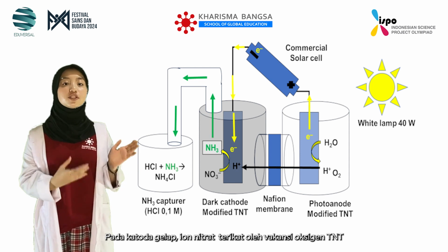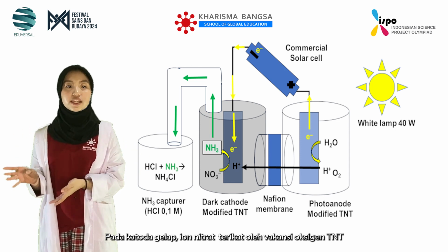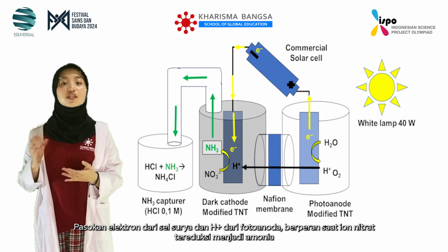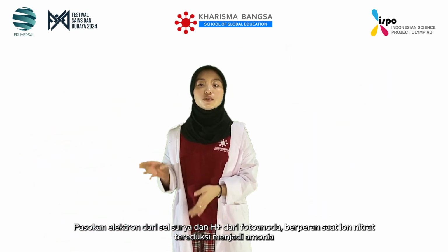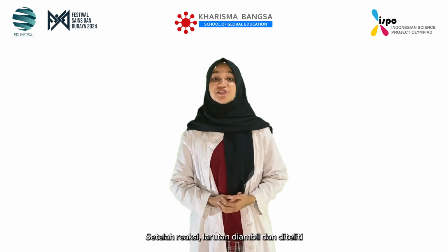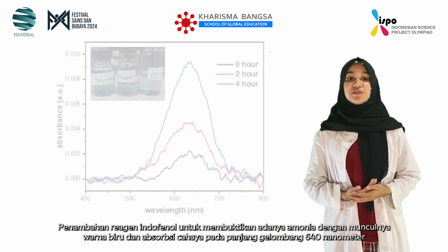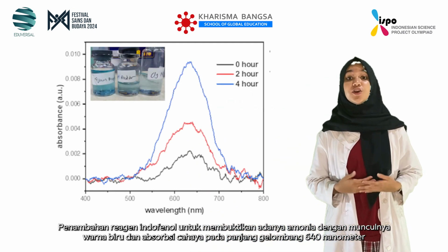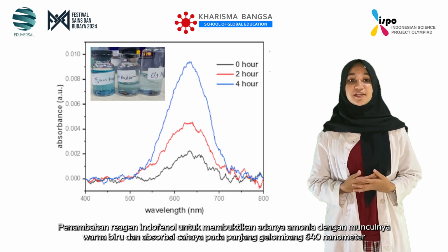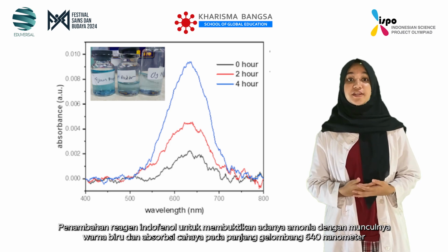On the dark cathode, nitrate ion bonds to TNT oxygen vacancies. With electron supply from the solar cell and the H+ from the photoanode, nitrate ions are reduced to ammonia. After the reaction, the solution was taken. The addition of indophenol reagent revealed the presence of ammonia through the emergence of a blue color with maximum light absorbance at wavelength 640 nanometers.